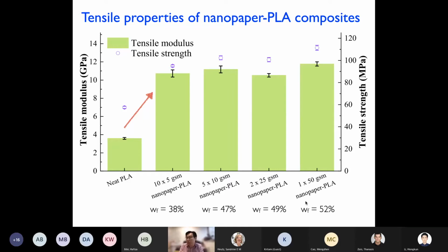Again, this is because the nanopaper themselves actually have a high modulus and high strength stemming from the performance of the individual nanocellulose fibers themselves. So we are able to achieve a tensile modulus of approximately 10-11 gigapascal and a tensile strength of roughly 100-110 megapascal there.